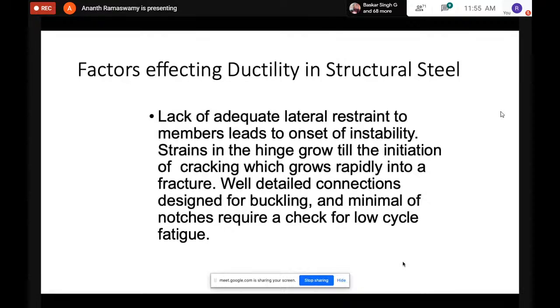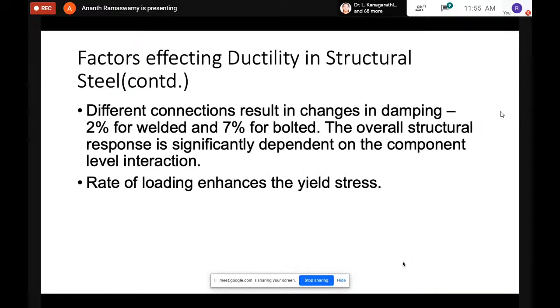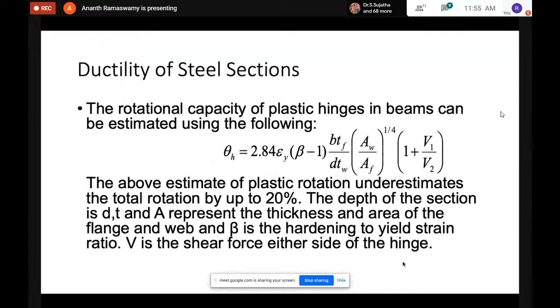Lack of adequate lateral restraint can lead to instability, strains in hinge growth till initiation of cracking, which grows rapidly into a fracture. You can always have joint fracture, weld breaking, buckling. So there are so many different modes. You really don't have a clear idea what is playing an important role in the failure mechanism. The rate of loading enhances yield stress. Different connections result in changes in damping, 2% for weld, 7% for bolting, etc. Rotational capacity at hinges, these are expressions that you can find in the literature.